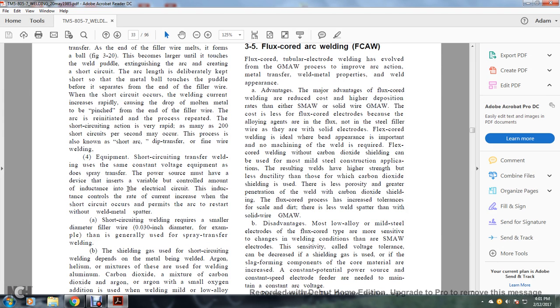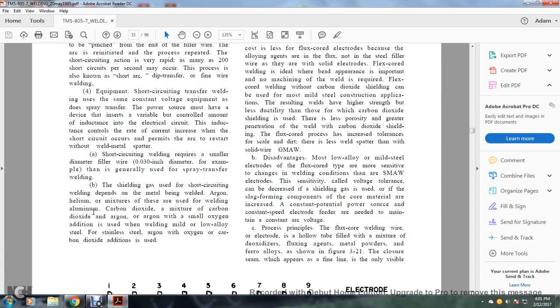For equipment, short-circuiting transfer welding uses the same constant voltage equipment as spray transfer. The power source must have a variable inductance control that controls the rate of current increase when the short occurs, which permits the arc to restart without welding spatter. Short-circuiting welding requires a small diameter filler wire, 0.030 of an inch in diameter, for example, which is generally not used with spray transfer welding.